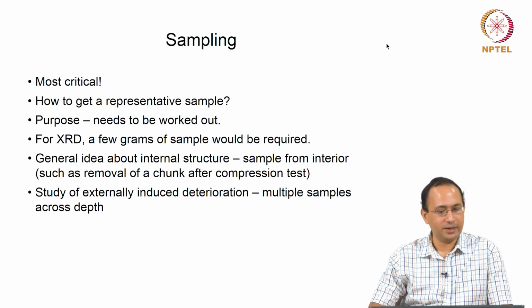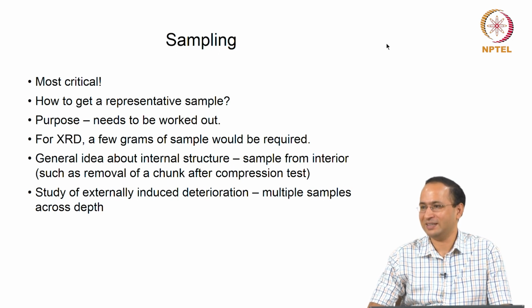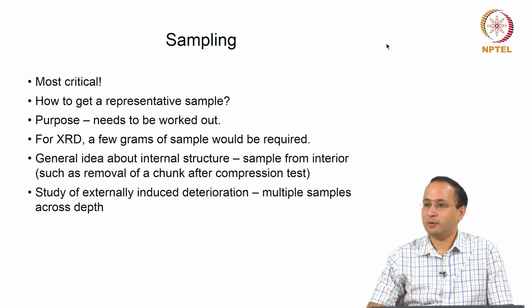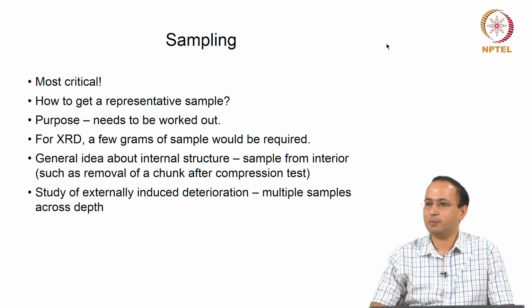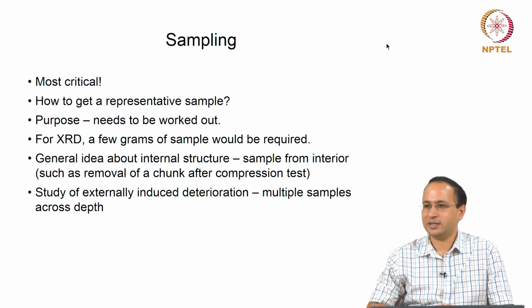So for an example, for XRD, a few grams of sample would be required, but for strength determination a few grams will not do anything, right. So it depends on the goal, what you want to achieve. You also need to have a general idea about the internal structure, so sample from the interior. For an example, if you are doing a compression test, after the compression test you may have induced micro cracking in a lot of samples, right. So you have to be aware of that. You want to make sure that the sample you are taking is free of that. If you are looking at microstructure for an example, the internal cracking will affect it, and you will not be able to determine a lot of characteristics.